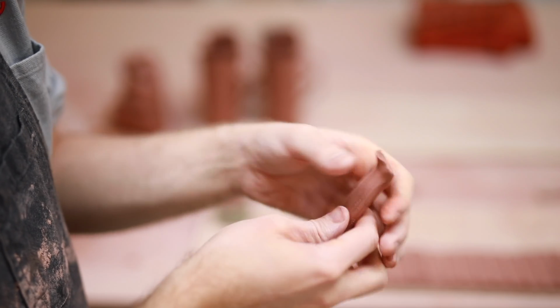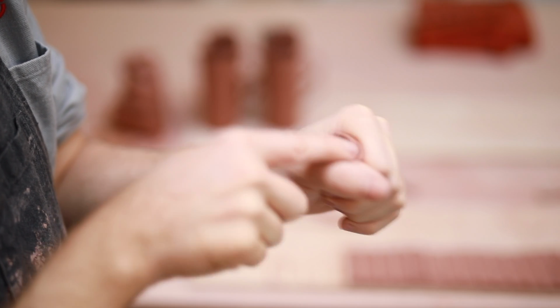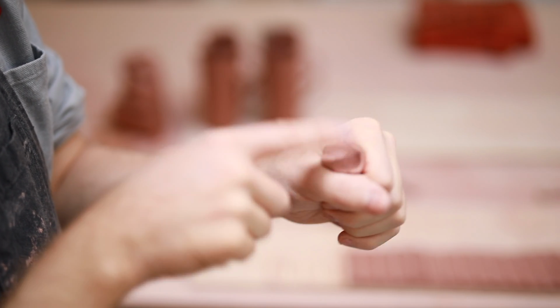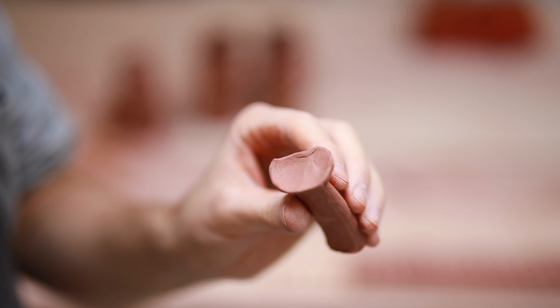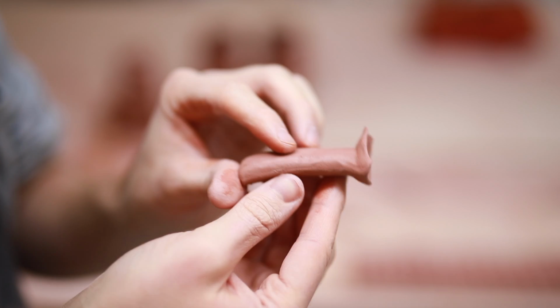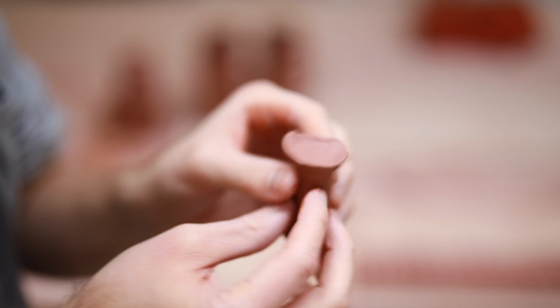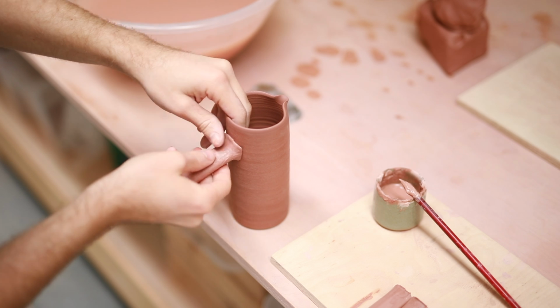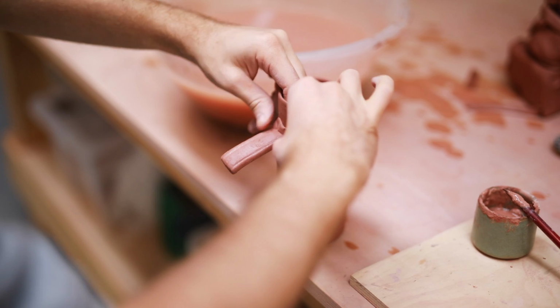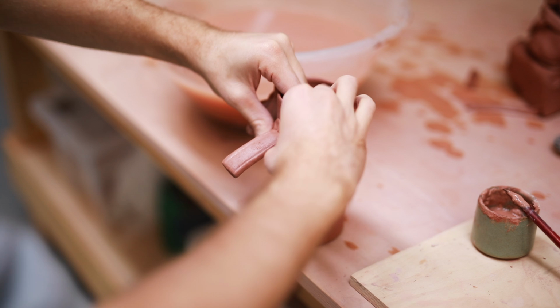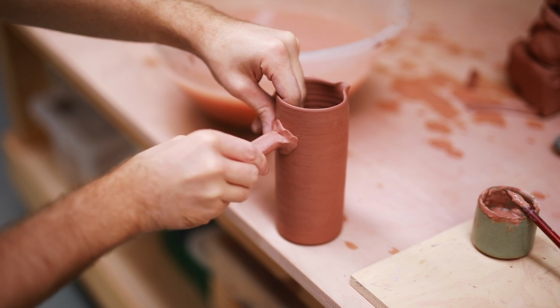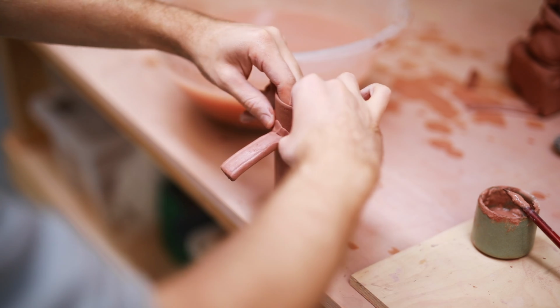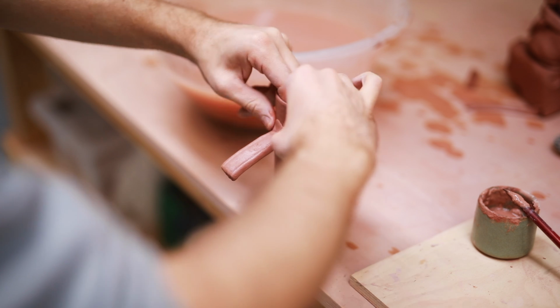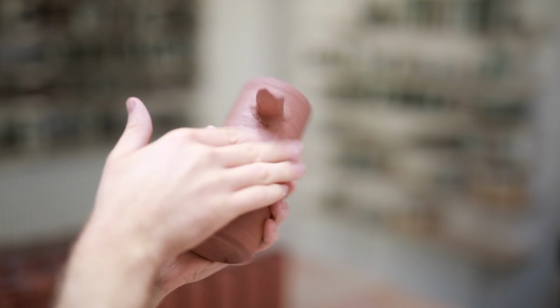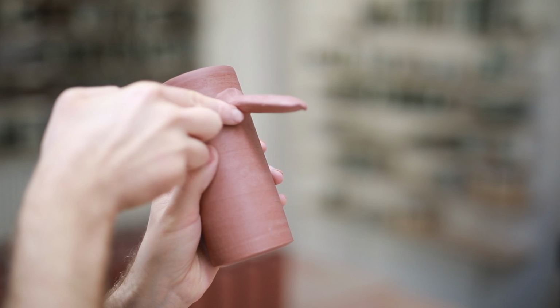I then take one of these blanks and begin to tap out one of the ends, which creates a flare. This flare will provide material that's easily blendable into the wall of clay, and therefore makes the process of attaching the handle to the pot before you pull it much easier. I then firmly push the handle blank onto the pot, making sure there are fingers inside the vessel, counteracting the pressure pushing inward the whole time. I then use a dry finger just to smooth this clay in, which creates a very strong join.